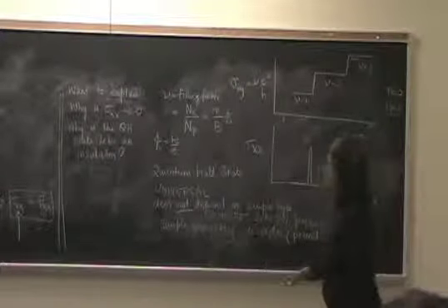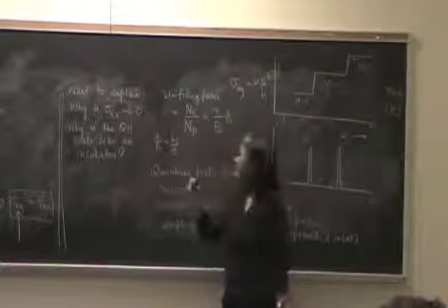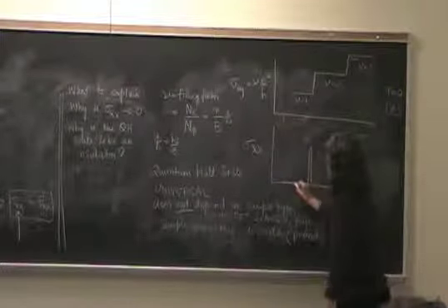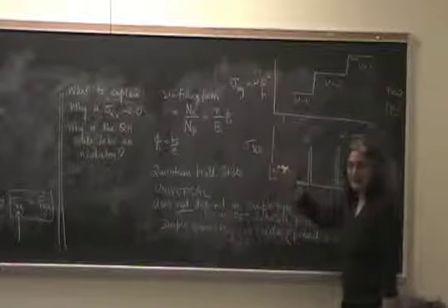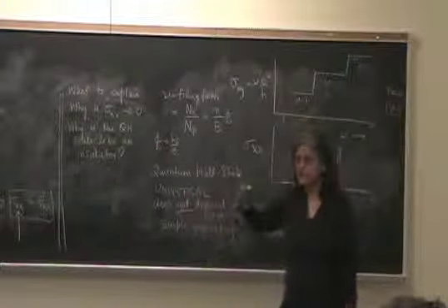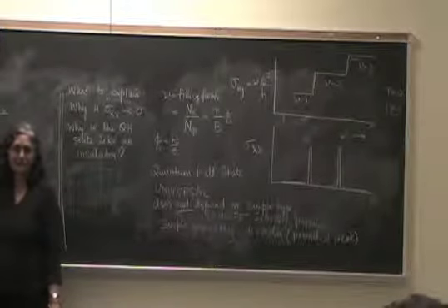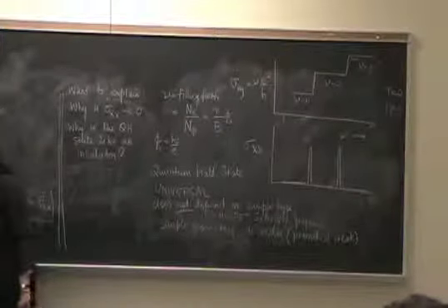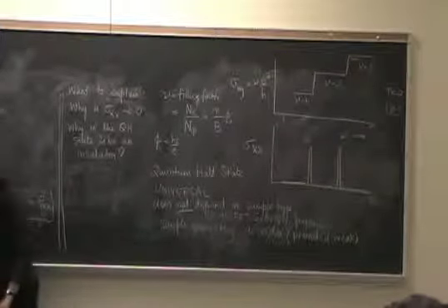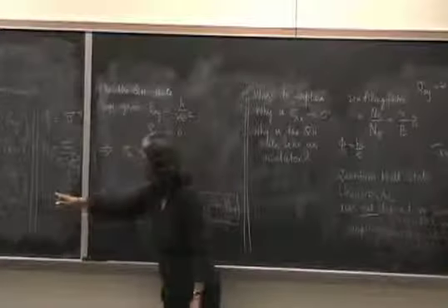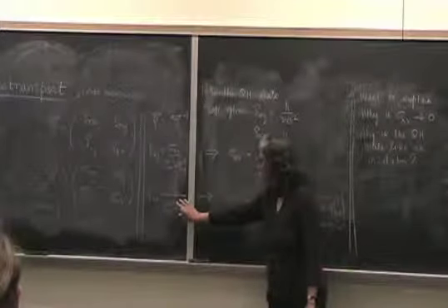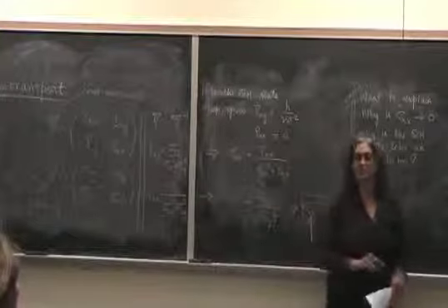What I'm trying to say is the insight comes from theory in the following way. We will explain why conductivity is going to zero in this region, because the system is becoming some kind of insulator, which I will describe. Once we understand that, we then resort to just mathematical properties of inverting a matrix with a denominator which is finite. Had sigma xy been zero, then indeed you get your usual result, rho xx is 1 over sigma xx. It's only because sigma xy is finite that you get this result that rho xx is proportional to sigma xx.